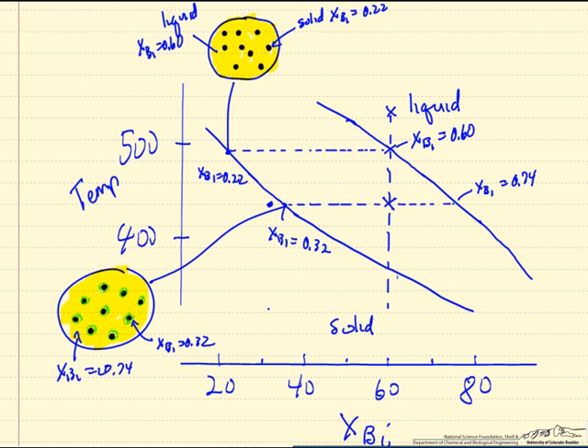What this means when we look at the lever rule now is we actually have more liquid than we would have if we were at equilibrium. And so as we cool, there's some continuous line of this non-equilibrium, and the non-equilibrium continues.